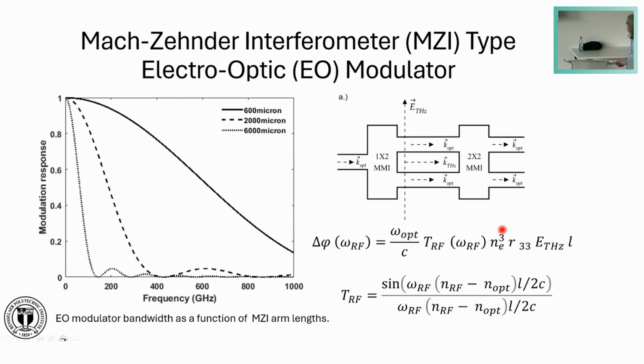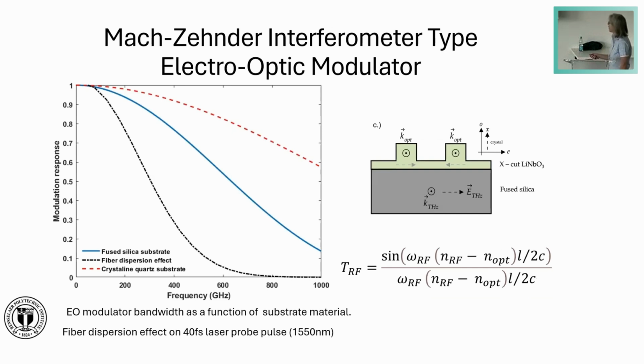We also see that the transfer function, the modulator response, is frequency dependent, and this is determined by the difference between the index of refraction for the terahertz wave and the optical wave, because they determine the speed at which the two waves are traveling. If they are matched, if they have the same value, we basically have an infinite bandwidth. So we can detect the frequencies over a large range, and the more they differ, the smaller the bandwidth will be.